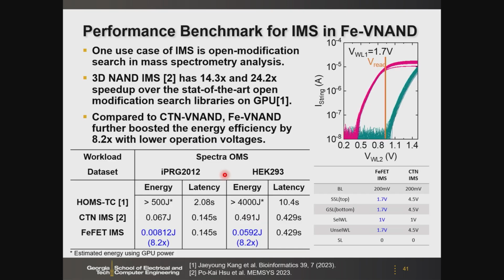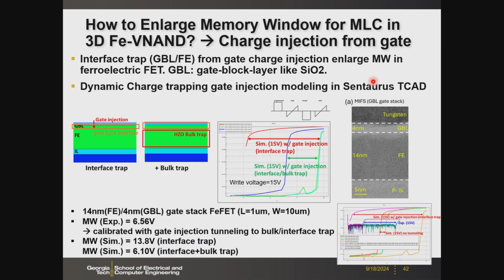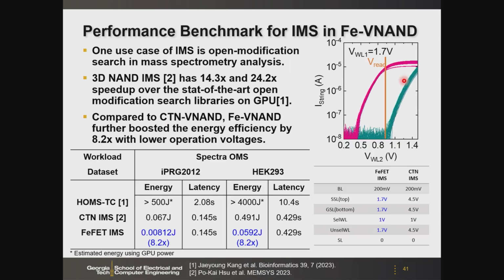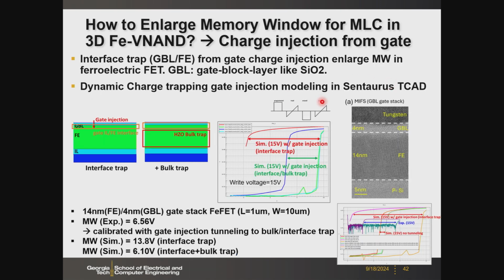So how could Ferro help in this application? Here the Ferro has much lower program and erase voltage and read voltage than the charge trap based NAND. Therefore, we can further reduce the energy and latency for this kind of pattern matching problem in the 3D NAND. I've skipped the details due to the time limit. And the last slide. Here, one challenge for the Ferro, if we use it for the NAND, is the memory window is kind of small. And then how do we increase the memory window in the FeFET NAND?